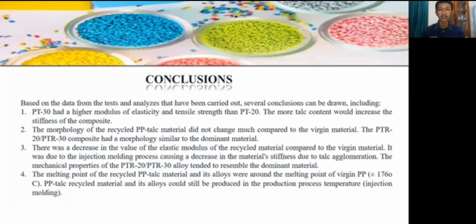And the end, conclusion. Based on the data from the tests and analysis that have been carried out, several conclusions can be drawn, including: 1. PT-30 had a higher modulus of elasticity and tensile strength than PT-20. The more talc content will increase the stiffness of the composite.